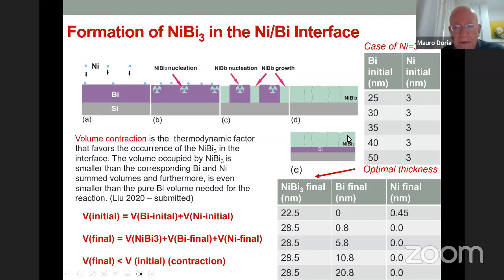And what's very interesting about this system from a thermodynamical point of view is that you have an initial volume, an initial quantity of bismuth and an initial quantity of nickel that you deposit. And then finally, you have a volume of nickel bismuth 3. Let's ignore the other one. I'll assume that everything is nickel bismuth 3, because you can, in fact, have the formation of two compounds. So I have nickel bismuth 3, and for the final volume you have a final leftover of bismuth and perhaps of nickel. And what you find out is that this final volume is smaller than the initial volume. So there is some contraction, okay?